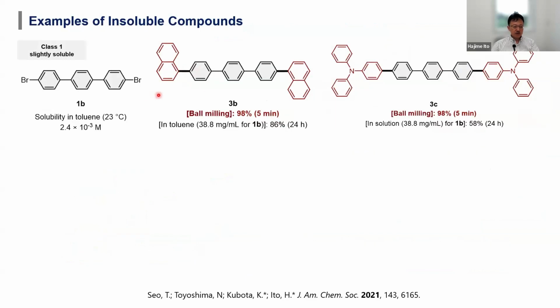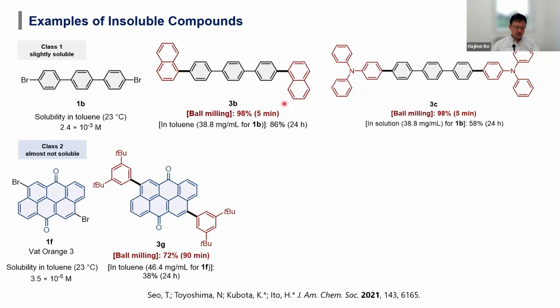So we tested other substrates. This substrate is similar regarding its solubility to carbon 60, but this works very nicely. Only 5 minutes is required for the ball milling reaction conditions.